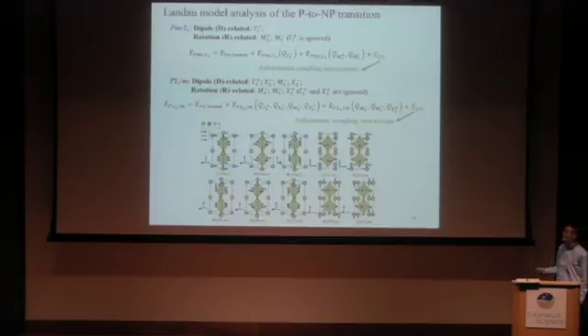We then use the Landau model to explain the macroscopic mechanism of the phase transition. Here in the polar phase, there are 3 modes. One is the polar gamma-5 minus mode, and the M2 plus in-phase rotational mode, and the M5 minus out-of-phase tilt mode. And in the nonpolar phase, there are 7 modes. There are 4 antiferroelectric modes, and the M4 minus out-of-phase rotational mode, and also the M5 minus tilt mode, and also the X1 plus tilt mode.